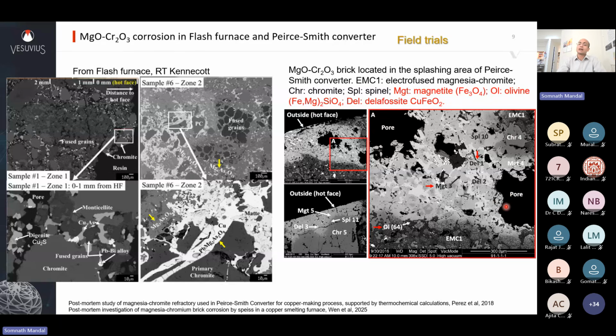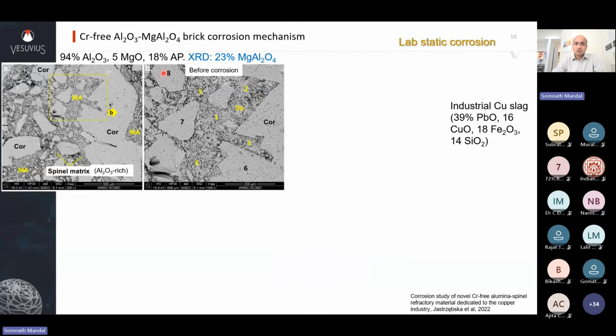So this is in general the corrosion process, and this is a slower process than with the chrome-free refractories you will see in a bit. So one of the most common chrome-free refractories, especially used in the steel industry, is the alumina spinel brick. You can see the alumina aggregates inside, and then you have a fine spinel matrix. So in this study these were reacted with an industrial copper slag. You can see the very high lead content, about 40% lead and 16% copper oxide. So a highly corrosive slag, much more corrosive than what you see in the steel industry.